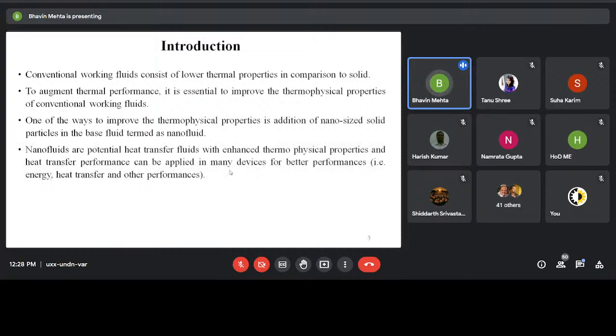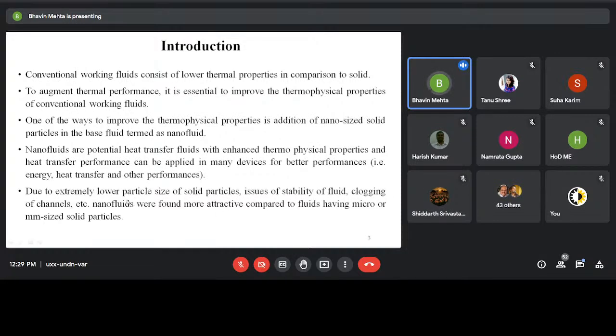Nanofluids are potential heat transfer fluids which enhance the thermophysical properties, improve the thermal performance of any device, and enhance the heat transfer rate. Now, due to the small size of the nanoparticles used to synthesize the nanofluid, the particle size may vary from 0 to 100 nanometers theoretically, but generally for experimentation the particles used are in the range of 20 to 40 nanometers.